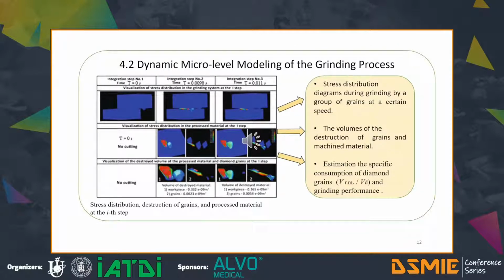Based on dynamic micro-level modeling, the stress distribution diagrams in the complex system diamond wheel, difficult to machine material during grinding by a group of grains at a certain cutting speed were obtained. The dynamic changes in the stress values were determined. Timing charts of the volumes of destroyed grains and machined materials were presented. The ratio of the removed material volume and volume of grain destruction was proposed to estimate the specific consumption of diamond grains. Grinding performance was estimated as the volume of the destroyed process material per unit of time.